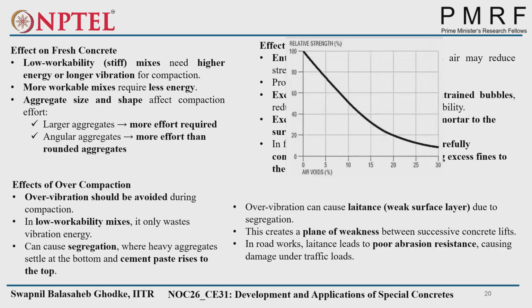Over compaction, what does it do? Over compaction should be avoided during compaction because in low workability mixes, it only wastes higher vibration energy. So we have to find out at what time we are getting the maximum density also. It can cause segregation where heavy aggregates settle at the bottom and cement paste rises to the top.